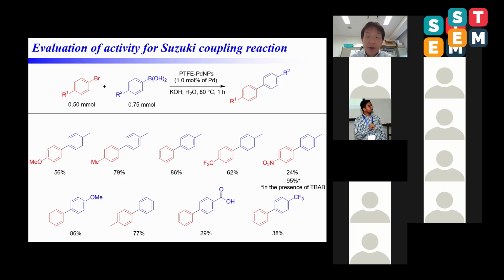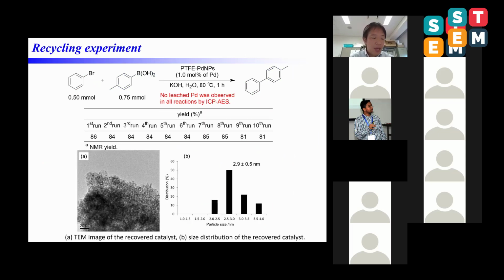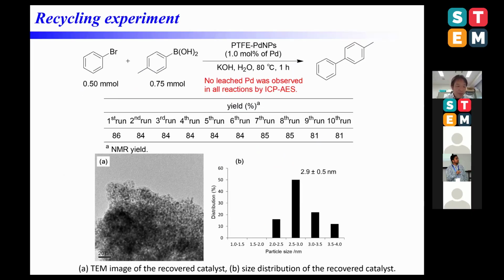And when the coupling reaction was performed using several arylboronic acids, the yield of coupling product decreased with decreasing electron density on the aromatic ring. When the recycling experiment was performed under these reaction conditions, the catalyst was recycled at least 9 times without any loss of activity. And no palladium species were observed in the reaction medium after the reaction as confirmed by ICP-AES analysis.